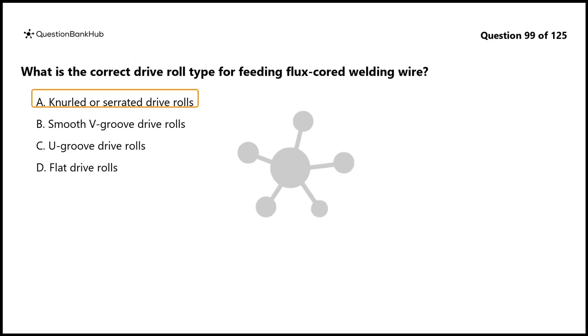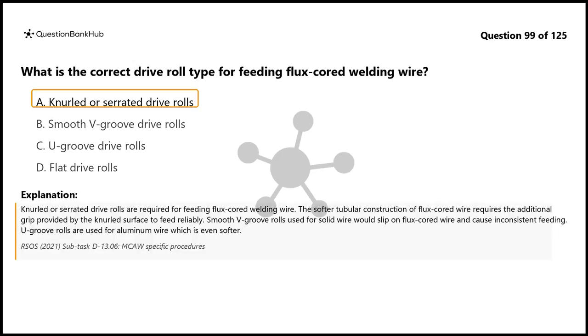Knurled or serrated drive rolls. Knurled or serrated drive rolls are required for feeding flux cored welding wire. The softer tubular construction of flux cored wire requires the additional grip provided by the knurled surface to feed reliably. Smooth V-groove rolls used for solid wire would slip on flux-cored wire and cause inconsistent feeding. U-groove rolls are used for aluminum wire, which is even softer.